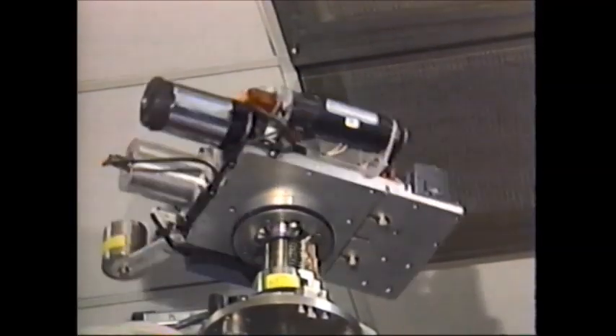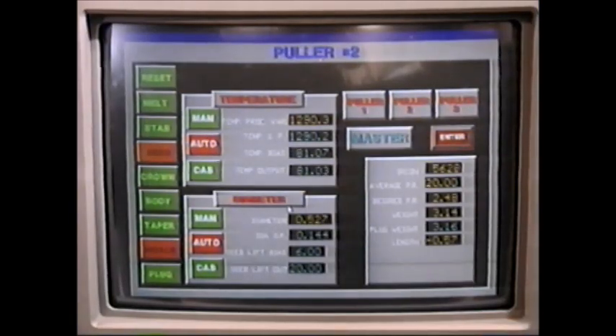The speed of the drawing mechanism varies, depending on the diameter of the finished ingot required. An 8-inch diameter crystal ingot may require a vertical pulling speed of 2 inches per hour, while a thinner ingot will require a faster rate.